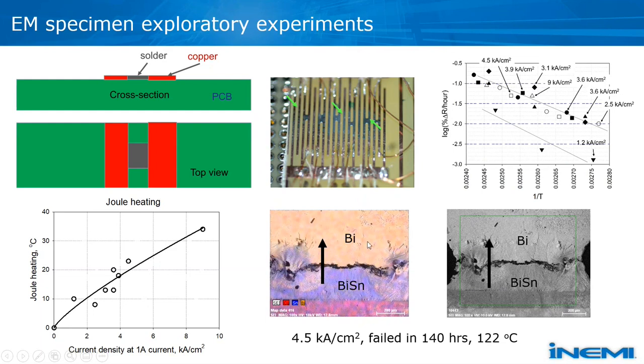The picture in the middle bottom is what's called dot mapping. It shows concentration of bismuth on the top and bismuth tin below that, so essentially the bismuth is segregated. Now, one issue with studying electromigration is to know the temperature of the solder joint. That's important, and we have a good technique of measuring the temperature of the solder joint very accurately. At the bottom left, I'm just giving an example of Joule heating above the ambient versus current density. You can see it's a very well-behaved plot: as you increase current density, the Joule heating goes up. And the picture on the top right is a summary of the data we collected, but I'll show that on the next page.